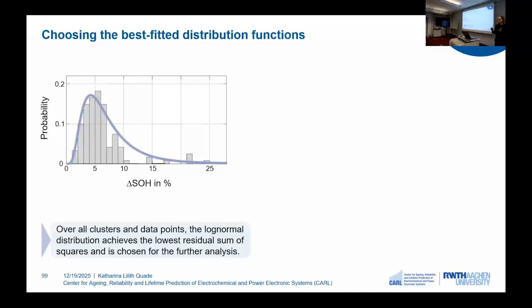So we now have our cluster space and different clusters, and we can proceed with the statistical modeling of our clusters. And here you can see on the x-axis the delta SOH values, delta SOH because we need a right skewed distribution of our data. Because we are analyzing aging data, it is naturally left skewed. However, almost most probability density functions are right skewed. And we compare different distribution functions and we assess different goodness of fit statistics. And we saw that for our clusters, the log normal function had the best goodness of fit.